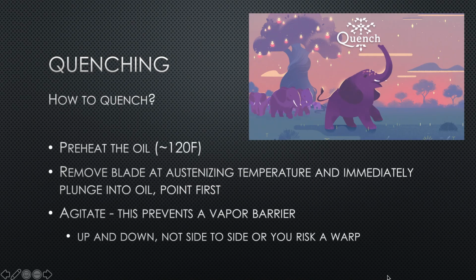So how do we quench? I'm going to talk mostly about oil quenching steels. We'll get into stainless later. But you need to preheat the oil. I know this sounds counterintuitive, but oil that's heated has less viscosity. It's thinner, and therefore it actually cools the steel quicker. So you do want to preheat your oil, and it's usually around 120 degrees depending on the oil and the steel.